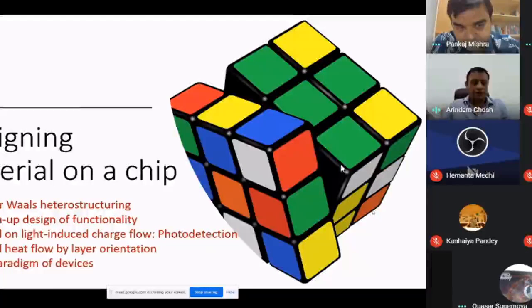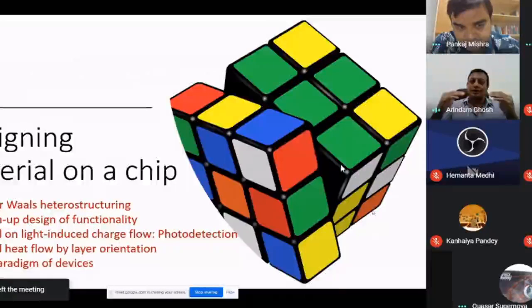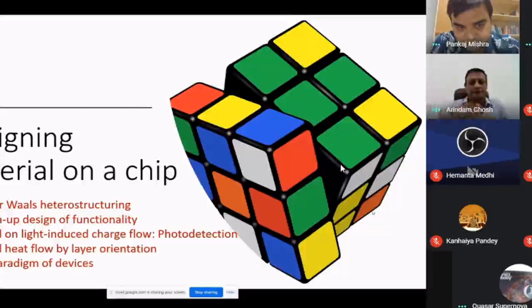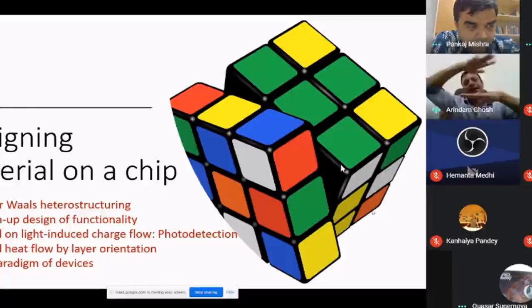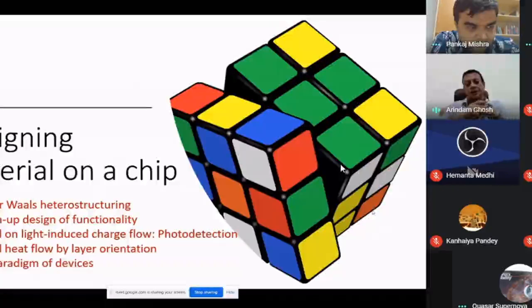So first of all, this question is certainly not irrelevant. This is a very important question of screening. And in fact, our referee of the thermoelectric data has actually raised several questions and objections, because often our analysis of the experimental data did not consider screening explicitly. For example, if you are looking at the lower layer of graphene, and we are applying a gate voltage from the top to populate the two layers and looking at its thermal or electronic properties, one layer will screen the top gate voltage to determine what is happening in the other layer.